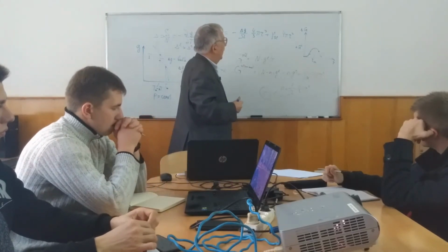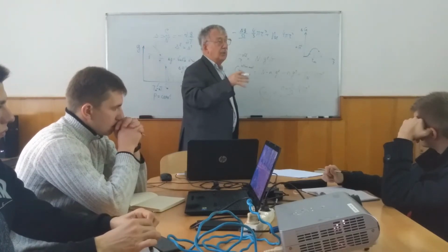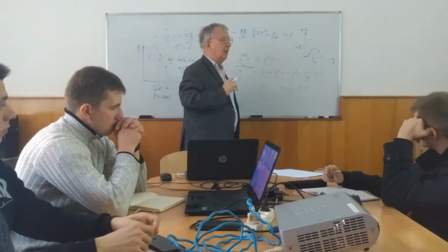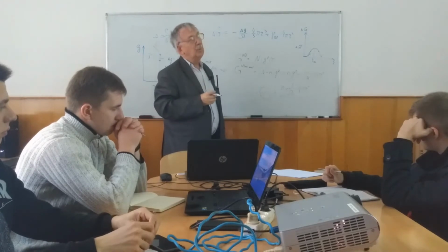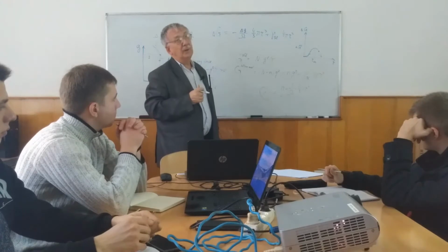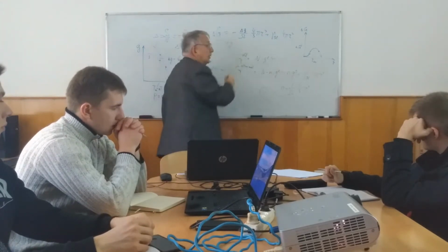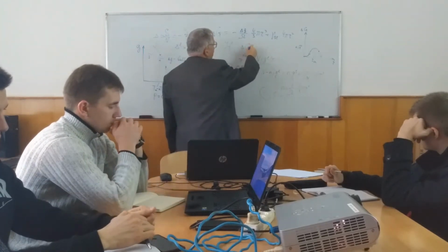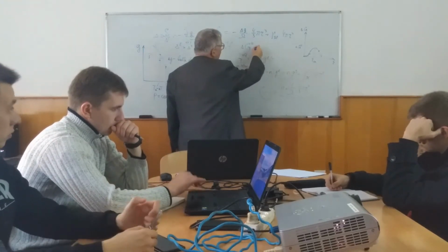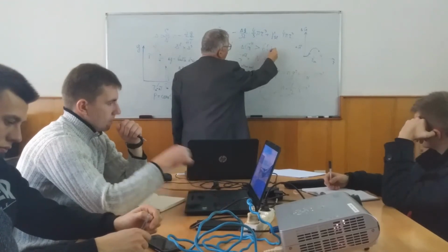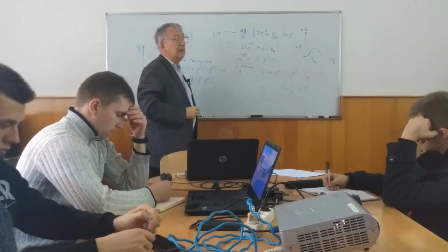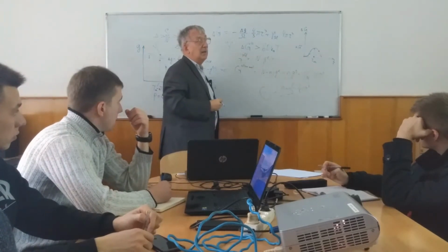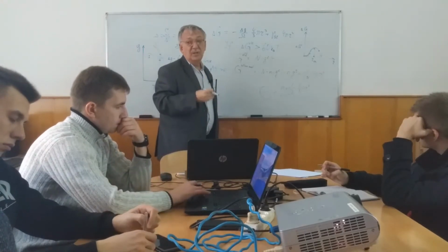Now, I'm not talking today about kinetics. I promised you to talk about kinetics in the next lecture. But I will tell you something kinetic. There is a well-known semi-empirical rule which is formulated in the following way. It's not proved rigorously even now, but it works. If the nucleation barrier is higher than 60 kT, where k is the Boltzmann constant and T is the temperature of nucleation, then nucleation is practically impossible within reasonable time.